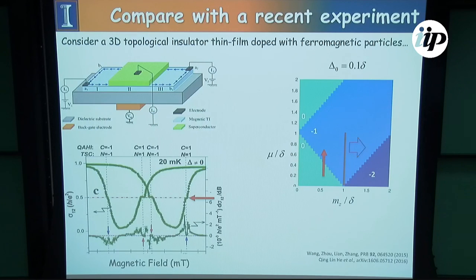And so this is an interesting experiment, certainly indicative of some theoretical predictions by Zhang's group, but it's not exactly quantized to half E squared over H. And just like Duncan Haldane said, if it's topological, then it shouldn't be half plus or minus 0.02. It should be half. So what I think is happening in this case is as soon as they're flowing a surface current, then there's a non-zero torque that opens within the system, the spatially varying Zeeman term, and this is what's causing it to be not completely quantized.